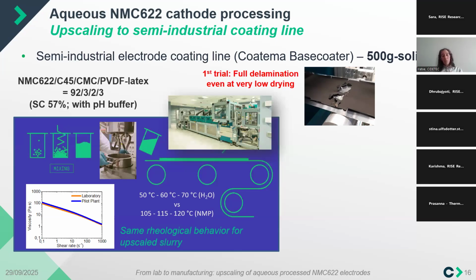When we went directly with this first upscaling that was working well with adjustments at lab scale, on the coating line we observed this huge issue of delamination—you can see it peeling off the electrode at the end of the drying, even when going at a slow speed to give more time for the drying step.